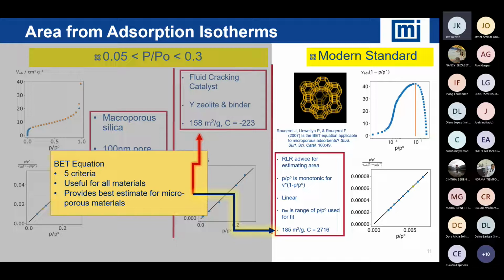The researchers at CNRS in Marseille, Rouquerol, Llewellyn, and Rouquerol, studied microporous materials extensively, and a great driving force for them was the emergence of metal organic frameworks. With metal organic frameworks, they realized they needed to take much more care in calculating surface area. So they came up with an additional set of rules for calculating surface area. One of them you see graphically in the upper right. You see this plot that looks like a volcano. And from that plot, now we understand that we can automatically select the correct range for calculating surface area. So using a new transform from Rouquerol to complement BET. It doesn't replace it. It helps us understand BET more in calculating surface area. So now we can select the correct range for calculating area.